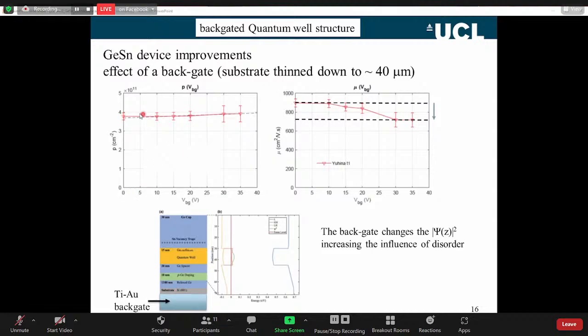We found using this technique here, we don't actually change the carrier density. This is the carrier density from a Hall effect measurement as a function of voltage. So we put 40 volts on the device there. Certainly wouldn't be of any use in the electronics industry if you have 40 volts there. What we did find was there was a small change in mobility. But what we thought was happening was we were just changing the scattering. We were just perhaps changing the shape of the quantum well and introducing some wave function sorting in the quantum well. We just see a scattering. We didn't see any proper changes in carrier density.